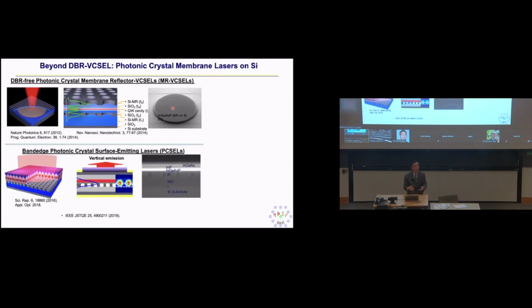And similarly, we can do so-called PCSELs I mentioned earlier. In this case, that's what we did before, actually: we designed a photonic crystal cavity structure, in this case, the PCSEL cavity. And then we can print 3-5, in this case, an indium phosphide quantum well structure at 1.55 micron on top to form this hybrid PCSEL structure as well. So we have been working on this actually for many years on these two types of laser structures.